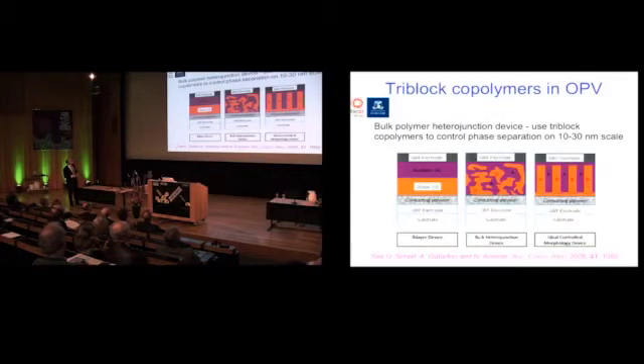And so this is the bulk heterojunction. We have a blend of a donor material connected to this electrode and an acceptor material connected to that electrode. And the idea is to have this surface area between donor and acceptor as large as possible, because the photoexcitation in the donor must generate an excited state which must move to this interface where the charges are pulled apart into the donor and acceptor within 10 nanometers. Otherwise, it will fluoresce or give out heat.